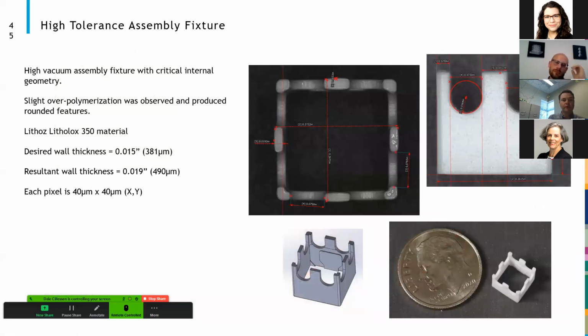Most recently, within the last few weeks, we've printed this high tolerance vacuum fixture. This high tolerance vacuum fixture has some very detailed geometry of a 15 thousandths wall thickness, or 381 microns. The resultant wall thickness we achieved was slightly larger. That's observable by the slight overpolymerization on these ends. We're down very, very small scale.